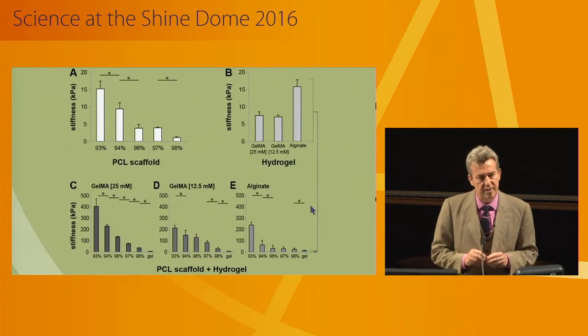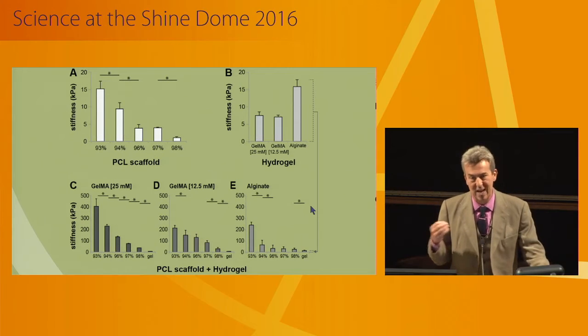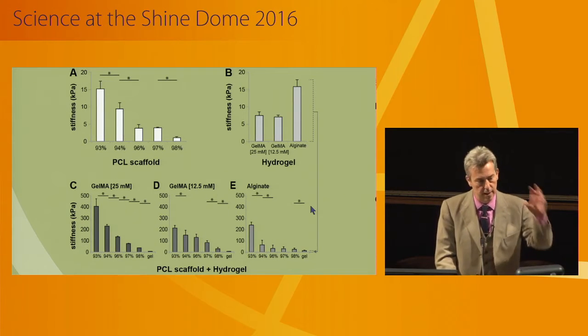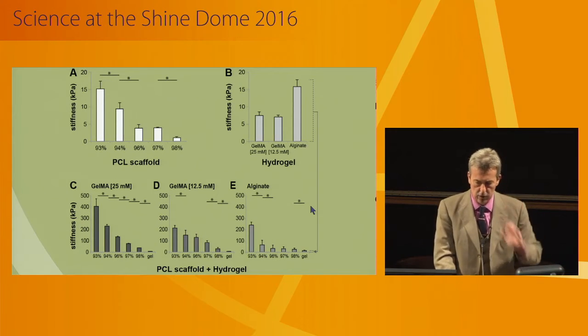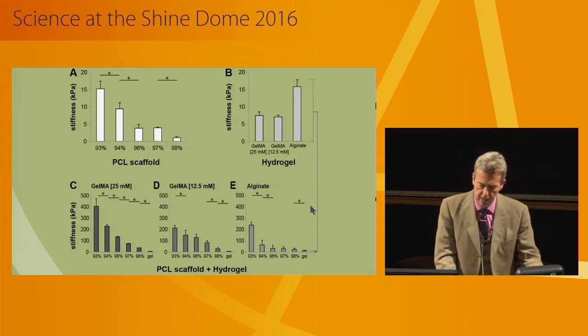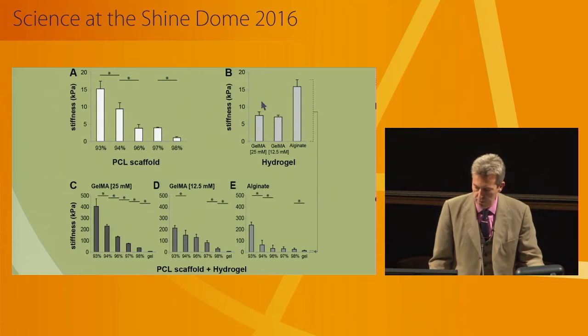But the problem is, when we think about articular cartilage, this is a high load-bearing cartilage. It has a multiple architecture. We talk about 4 zones. Cartilage has a stiffness of about 500 kilopascal to 1 megapascal. So when we look now at our meshes, you see here that we are at about 15 kilopascal, and as we increase the porosity, we go very low. If we take our hydrogels, then we are in a similar range.